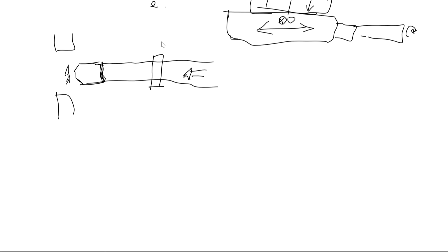We polarize the light, this is the polarizer. We shine light, so light comes to the sample, focuses on the sample, and then reflects back. So for the reflected light going back, we put a semi-transparent mirror, which is called a beam splitter, and that mirror would reflect the light reflected off the sample back. We would put it through another polarizer, which is called the analyzer, and a lens would focus the image into the camera.